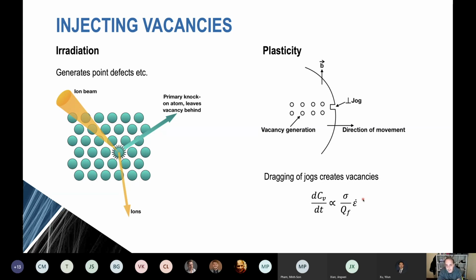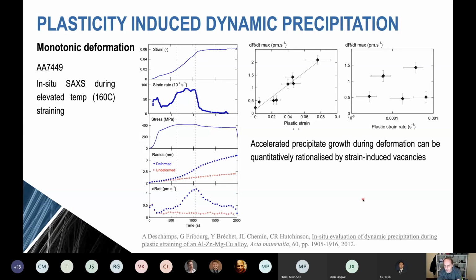And so the fact that we can use plasticity to drive mass transfer or diffusion, this is actually already well known. And so we've done lots of this sort of work in the past of looking at the coupling of plasticity and precipitation, and in particular the generation of vacancies, let's say strain-induced vacancies, to accelerate precipitation. And so this is an example in a 7000 series aluminium alloy. So this is an aluminium zinc magnesium based alloy, especially used in aerospace.